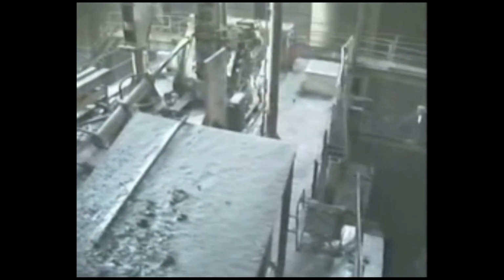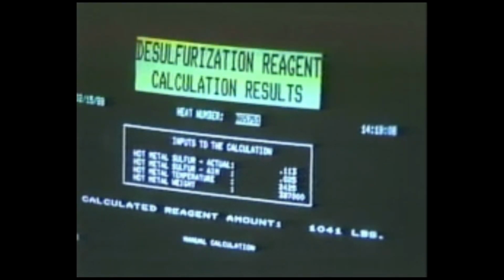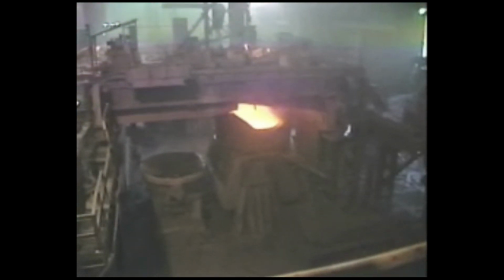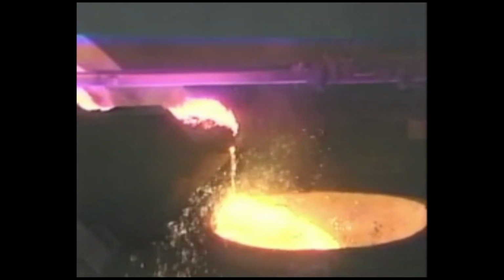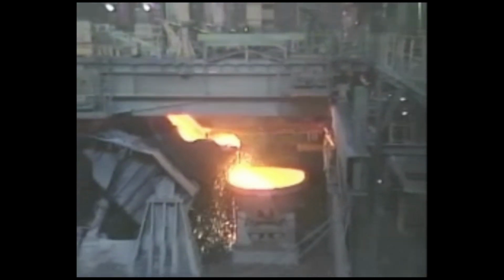At the desulfurization station, meticulous attention is given to reducing the sulfur content of the iron to extremely low levels, critical to the exacting surface quality requirements affecting the reliability of customers' products. We lowered a refractory lance down in there, and it's purged with nitrogen, and we inject 90% mag, and we blend it at a 4-to-1 ratio with lime. As the material rises up to the surface, it attracts all the sulfur, the magnesium, and it comes to the top as a slag. And then after we get done, we shoot our calculated weight. We'll go down and skim everything off the top, all the impurities and slag.